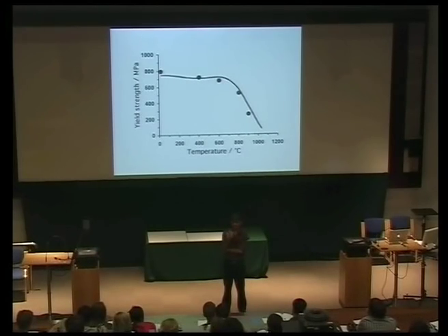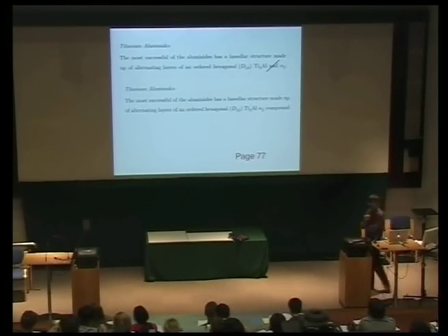Unfortunately, these alloys, pure gamma prime alloys, are extremely sensitive to impurities, and therefore their ductility can be very poor in commercial circumstances. So in a laboratory, we can make them incredibly pure and get lots of ductility, but in real life, that's not possible. So all that research in that sense didn't succeed. It didn't succeed in producing a material which is commercially viable. But in the process, a lot of other intermetallic compounds were examined.